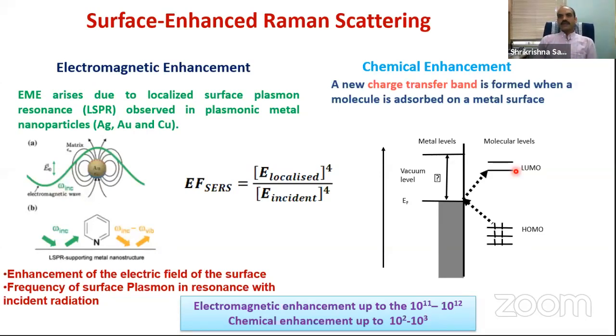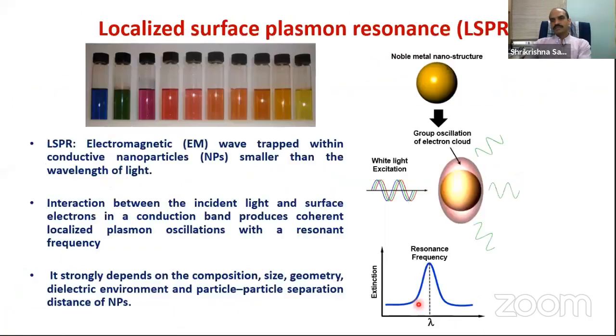Another enhancement is also there, that is what we call the chemical enhancement. So chemical enhancement will occur whenever the molecule is chemisorbed on the metal surface. Now there is physisorption and chemisorption. Chemisorption means there is a charge transfer between the surface and the molecule. Whenever there is charge transfer, you will have the chemical enhancement, which is a contribution of 10 raised to 2 to 10 raised to 3. However, the electromagnetic enhancement, which is because of this surface plasmon resonance, is of the order of 10 raised to 11 to 10 raised to 12. So this is a very significant contribution from the electromagnetic enhancement.